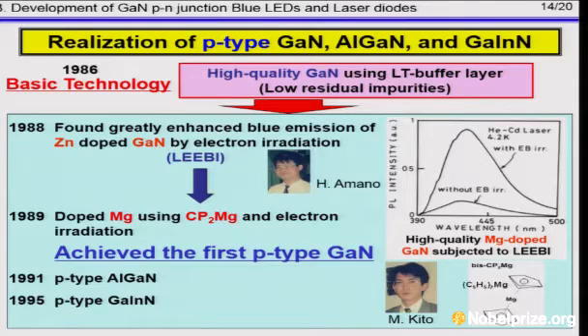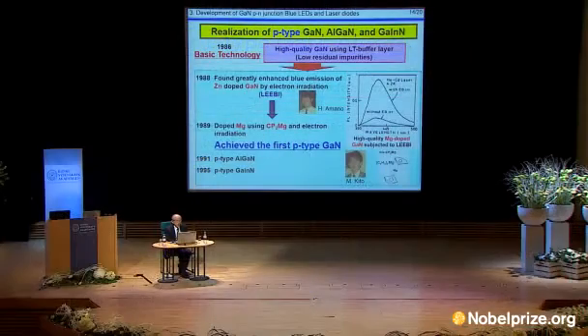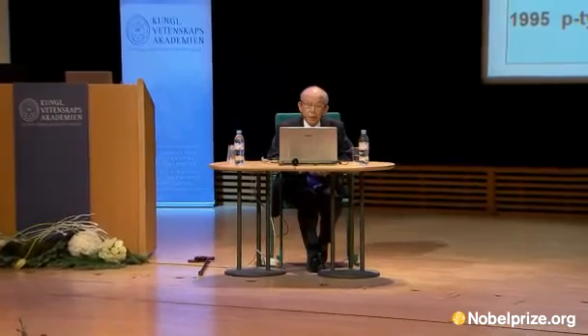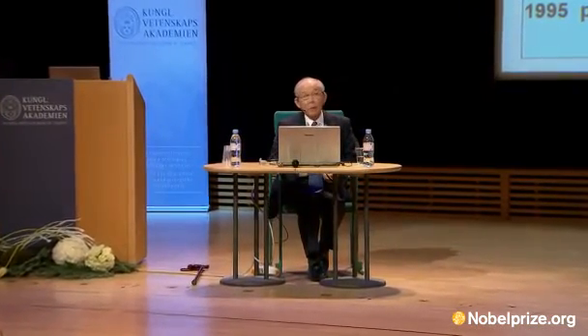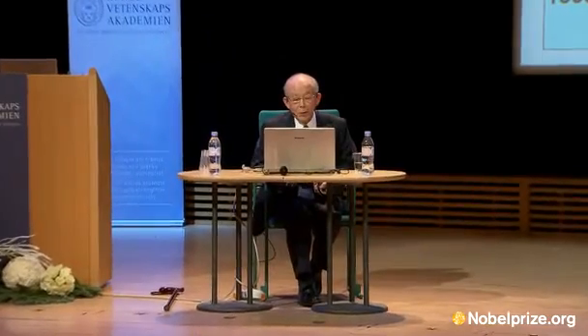In 1988, Hiroshi Amano found that low-energy electron beam irradiation markedly enhanced zinc-related luminescence intensity, while the spectral shape remained unchanged. We suspected that the Fermi level of the sample had been changed potentially to the p-type. Yet the sample did not exhibit p-type conduction.